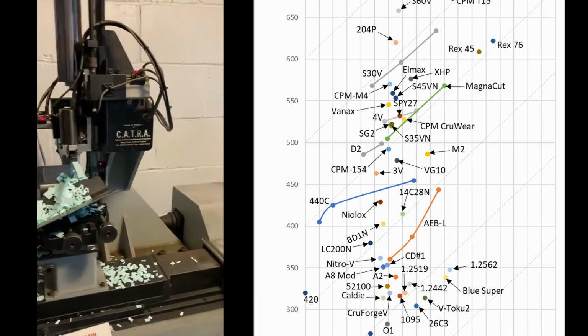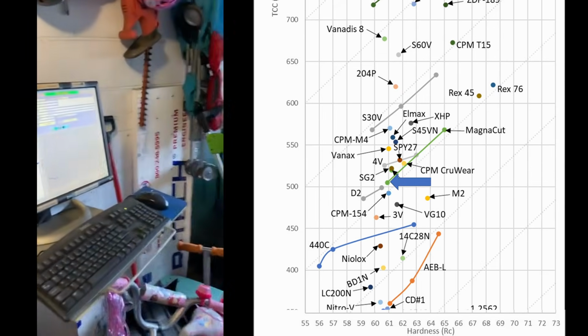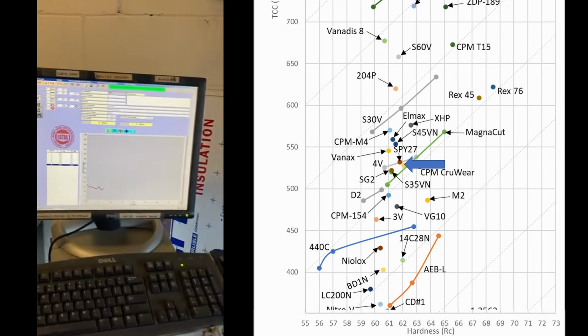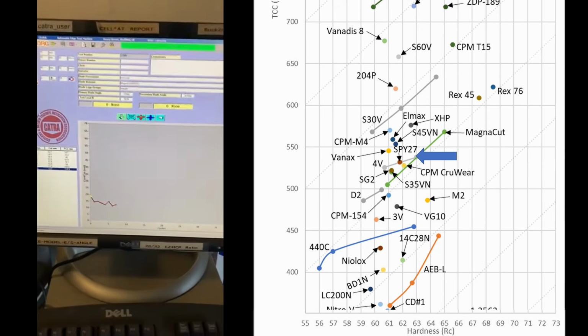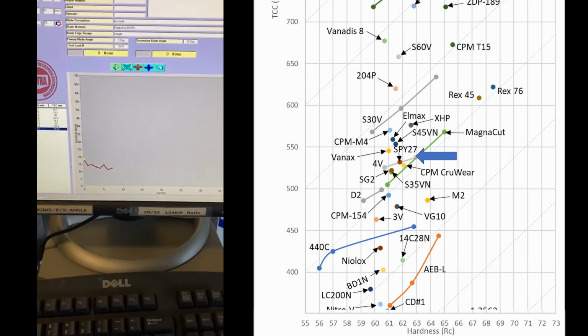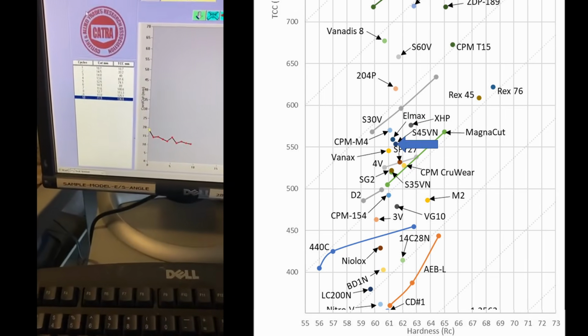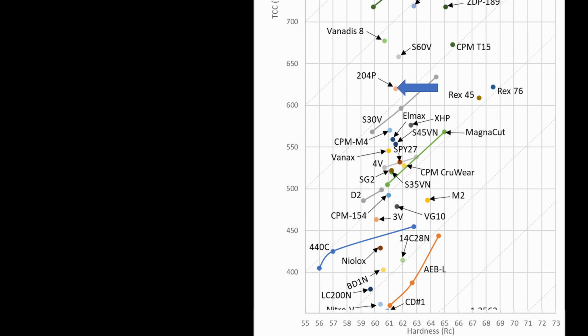MagnaCut has wear resistance approximately equal to steels S35VN, CPM CruWear, Vanax, and 4V. Those are all a small step down from S30V, S45VN, and M390 at equivalent hardness. MagnaCut at high hardness can match the wear resistance of a steel like S45VN at its typical hardness of 61 Rockwell C.